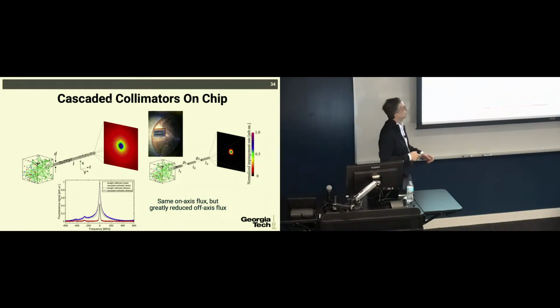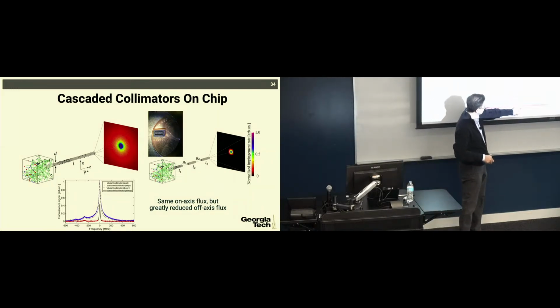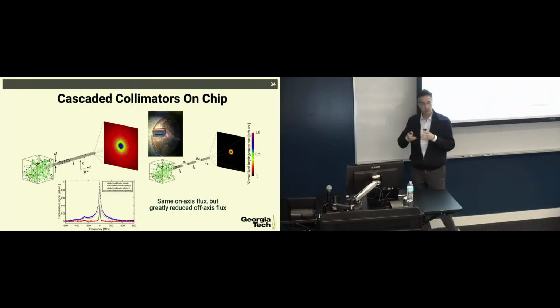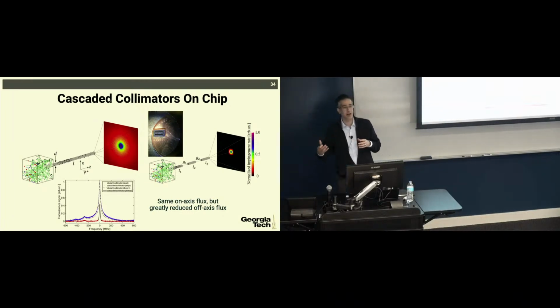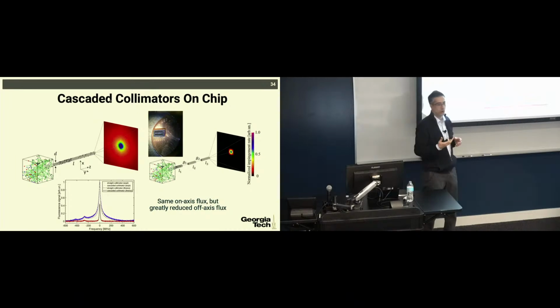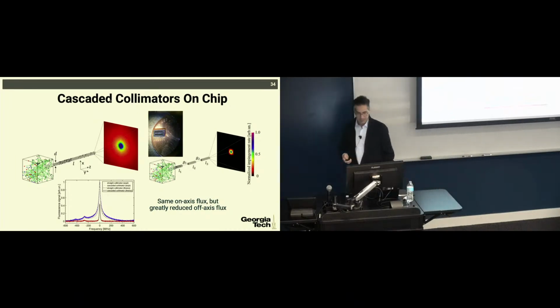Now, one thing that is enabled because of lithography is what is known as cascaded collimators. So not just one set of channels, but three of them in cascade, L1, L2, L3, and that would create the same on-axis flux but greatly reduce the off-axis flux. So the purity of the resonances becomes much, much better as you cascade these collimators. It's becoming almost like a high-Q resonator, so the quality of sensing becomes a lot better.